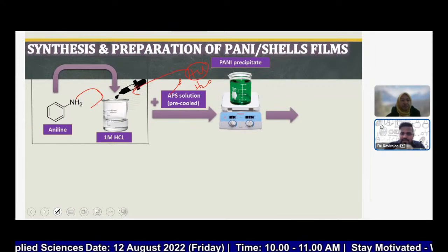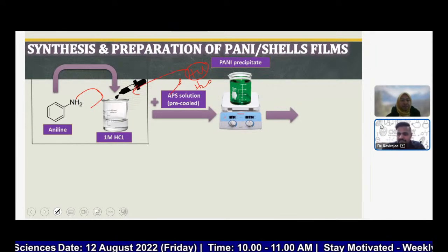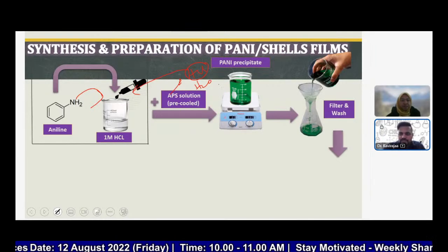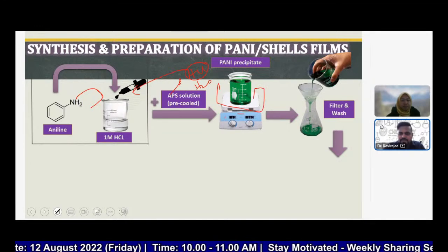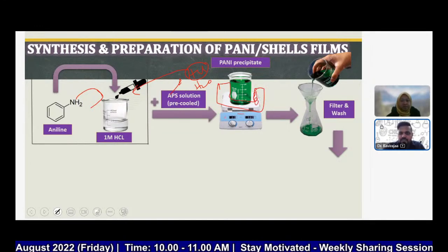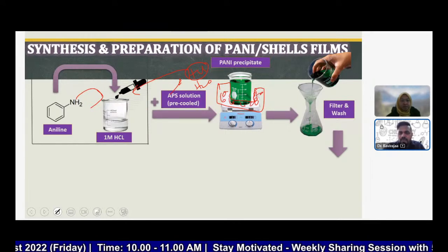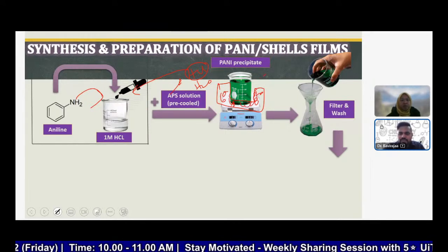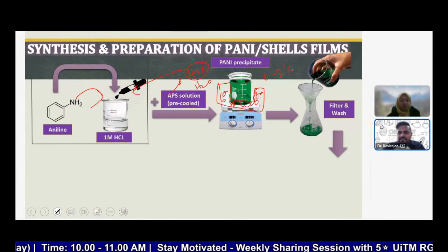And then we will add it. So here, one of the steps that I think I didn't show is we use a polystyrene box and then we fill it up with ice cubes overnight. We wanted to make sure it stays at 0 to 5 degrees Celsius.